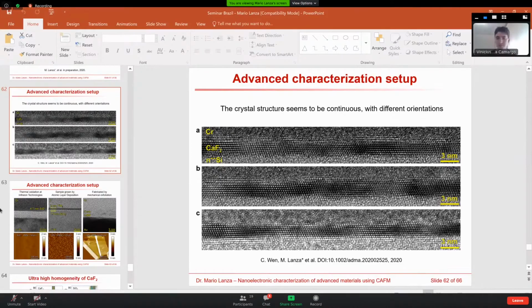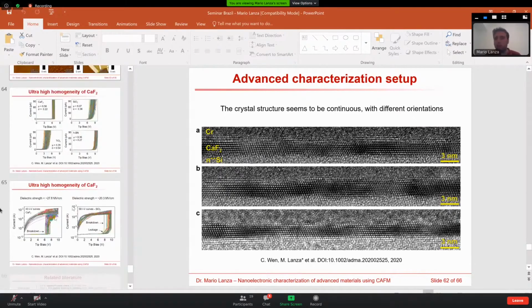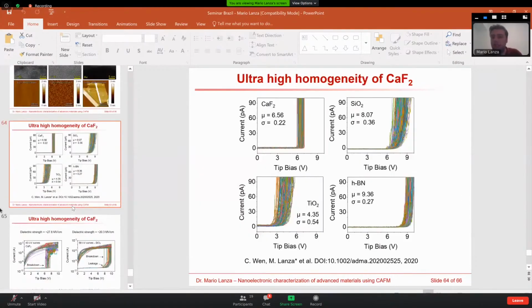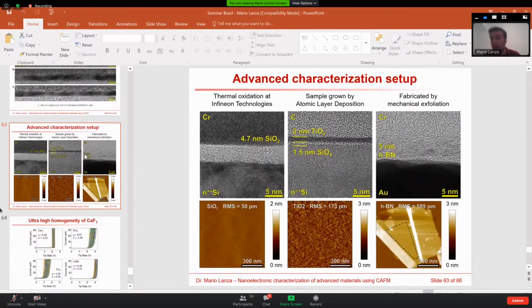Okay, so let me start with the second. For calcium fluoride, the material that we have analyzed in this study is 2.5 nanometers. With only 2.5 nanometers, we observe an onset potential of 6 volts, which is similar to the onset potential of silicon oxide when grown by thermal oxidation, and the silicon oxide is, as you can see here, 4.7 nanometers. So it is a really, really good dielectric. With only 2.5 nanometers, you can already have something that is quite insulating.